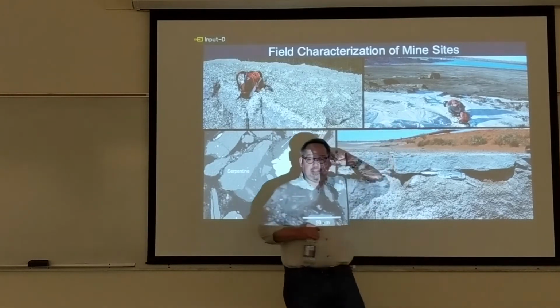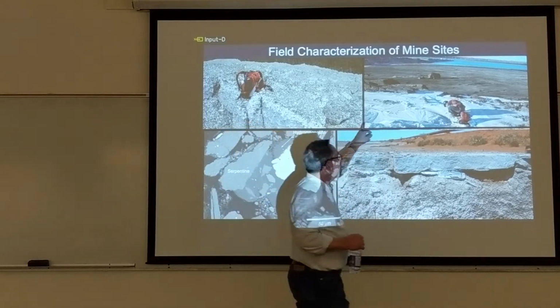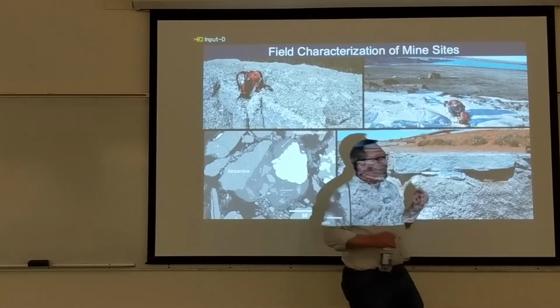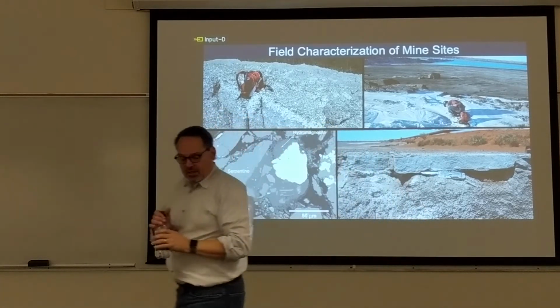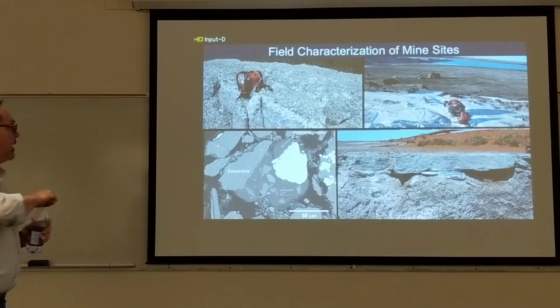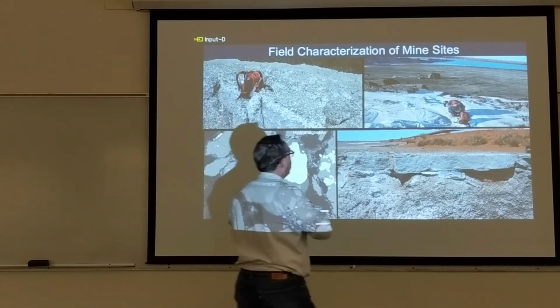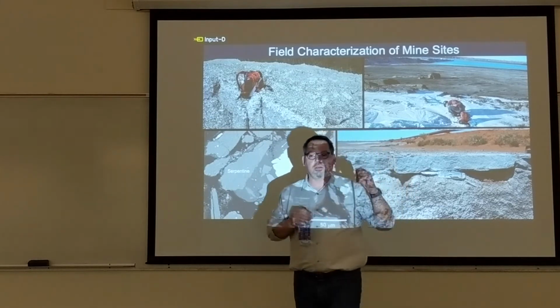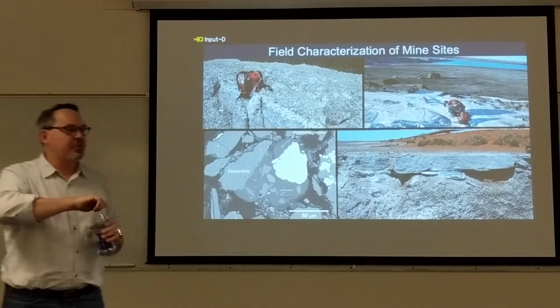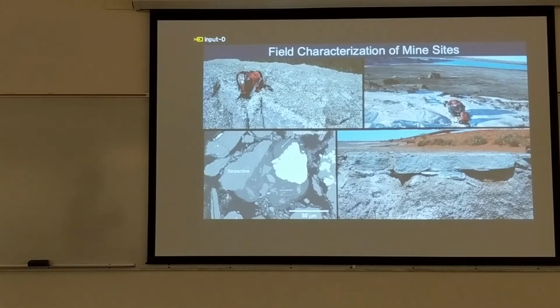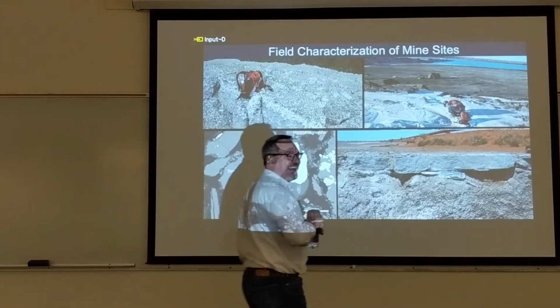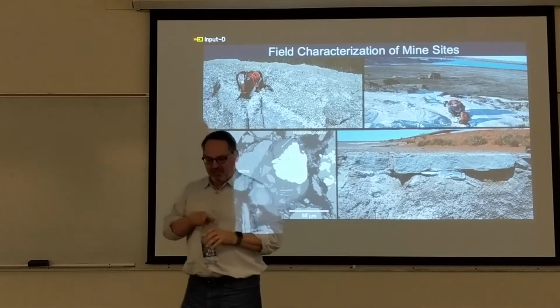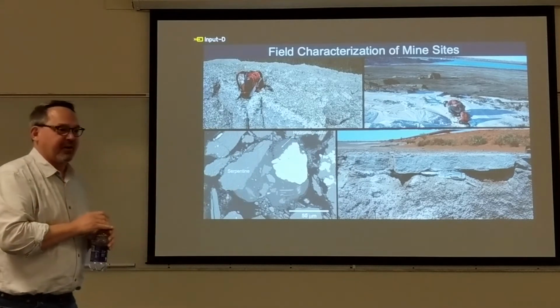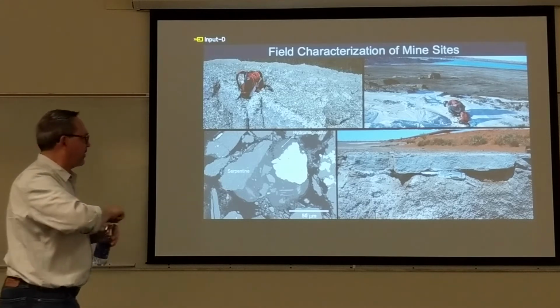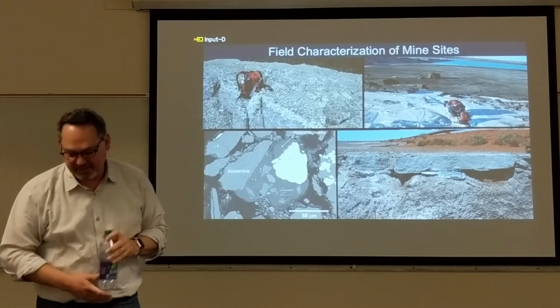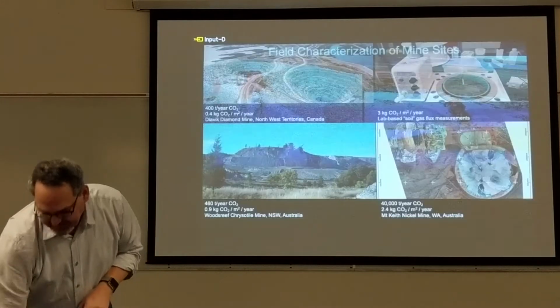Sometimes when we have point sources of CO2, we find a lot more reaction, so there's quite a bit of carbonate in these crusts. We were very intrigued, trying to figure out what the point source of carbon was at Diavik. And when our hosts came back from their lunch break, they told us this is where they have their treated sewage. So mineralizing the mine sewage. That was after we taste tested for it. So we got off there pretty quickly. But anyways, we can measure the carbon-13 of the carbonate minerals there, and you can actually see the organic 13C signal of essentially carbonated sewage.